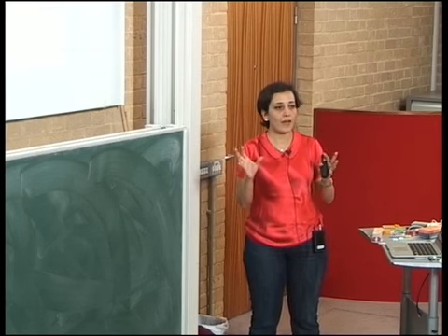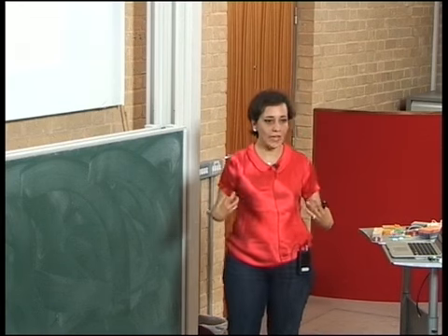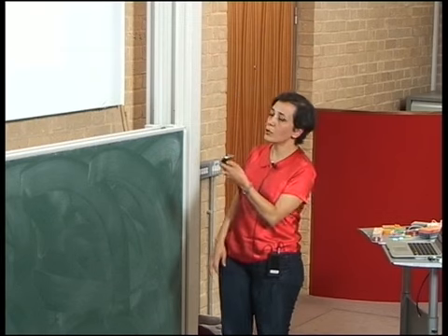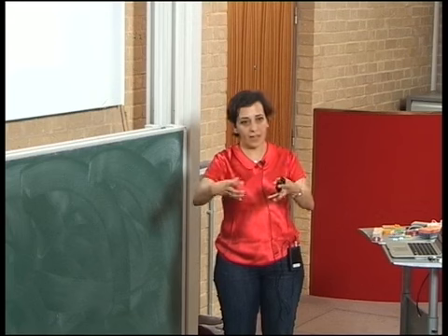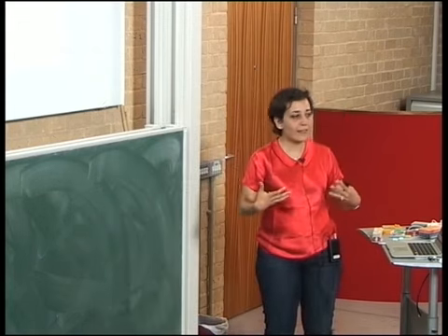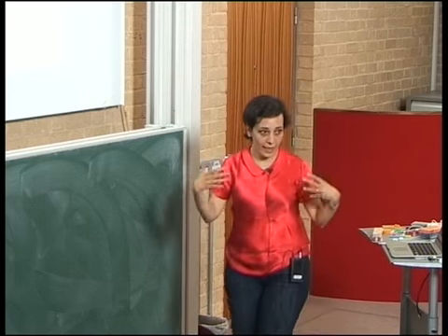In this case, we have extended this type of analysis to these dilute gels, where in fact everything is moving a lot. So it's not so easy to obtain the final information. So what we did is that we used this study that we had of the frozen network, the network with the frozen bonds, to actually subtract everything that comes just from the network vibration. Okay, so what we are left with is the displacements.